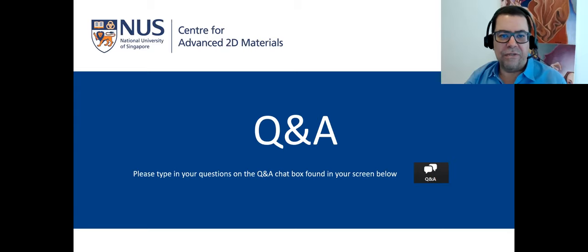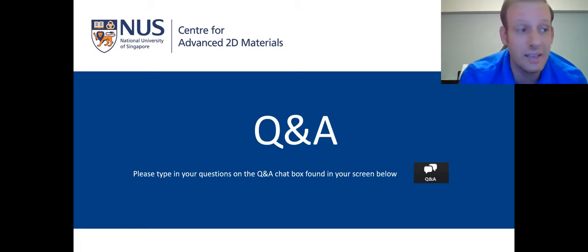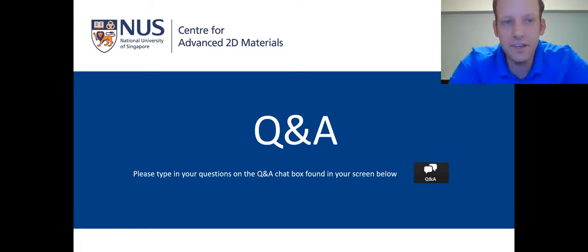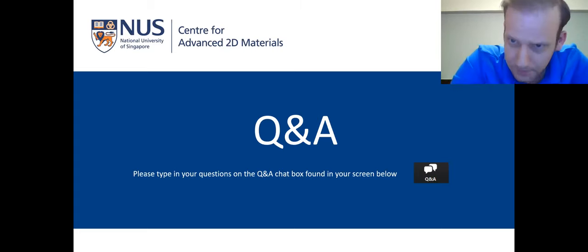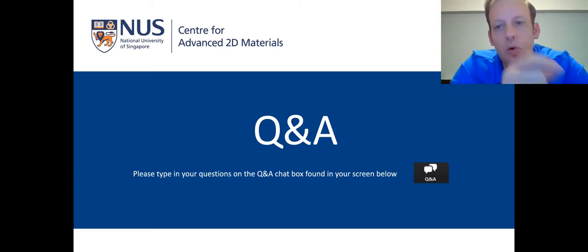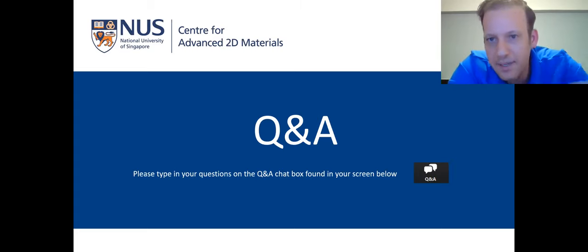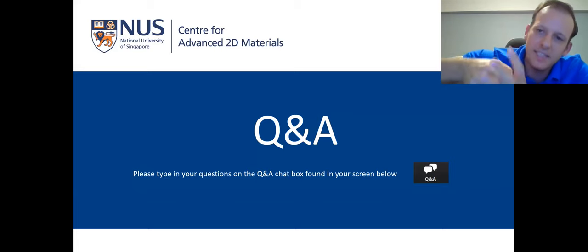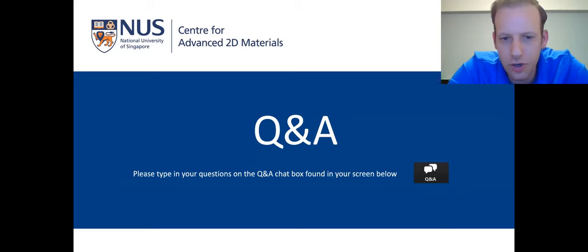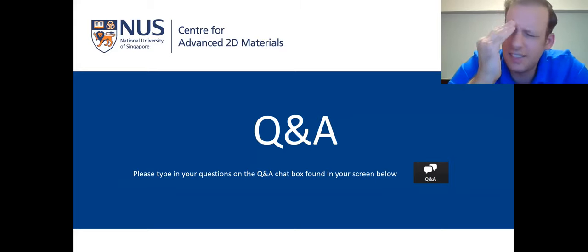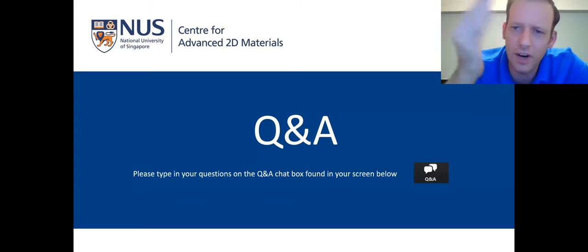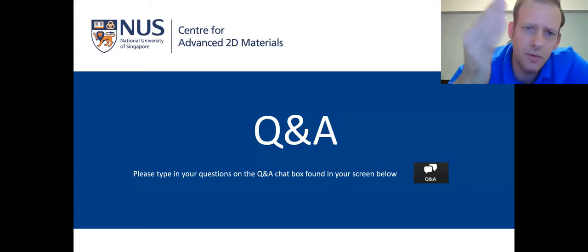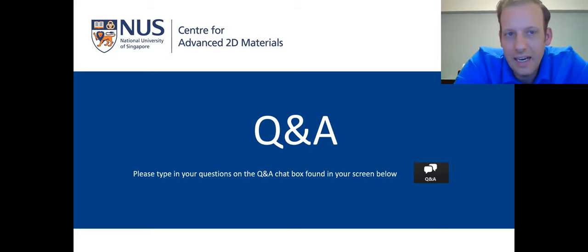Now, how long does it last on the surface? Okay, it lasts for a long time. Let me give you some examples of what we have done. We have put graphene on titanium on a real implant, and we have done a mock surgery in artificial bone. Why do I use artificial bone? Because artificial bone is way worse than natural bone. It's dry, very sharp, and very rough. And if we put our implants in and remove them, we still see graphene. We have actually published a paper in the Journal of Dental Research this year where we have done some friction tests, and we have data where we subjected our nanocoating to extremely harsh solutions for 8 months, and the integrity remains very high. So as far as we have measured, the structural integrity of the graphene nanocoating is not a concern.